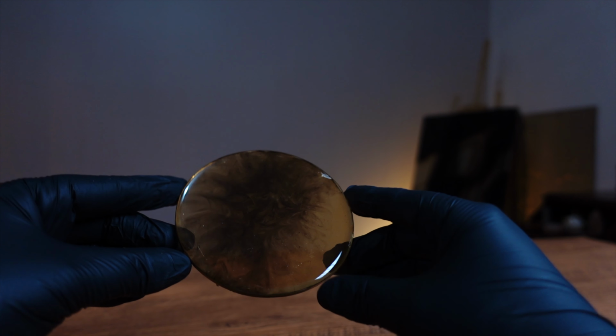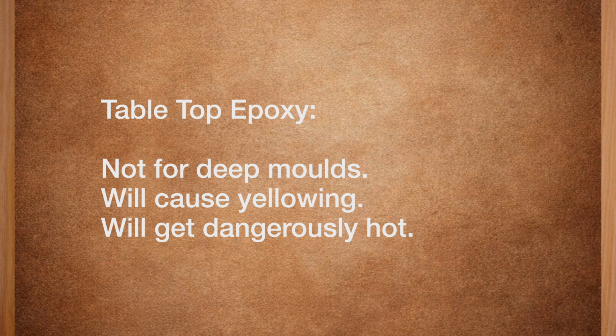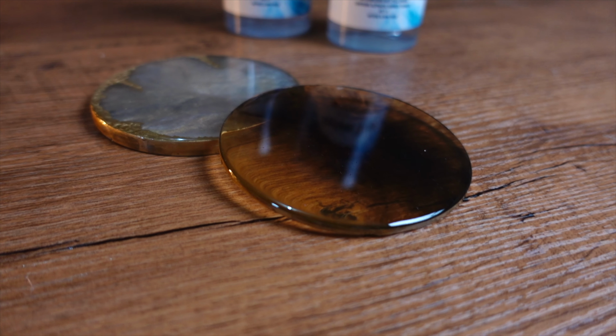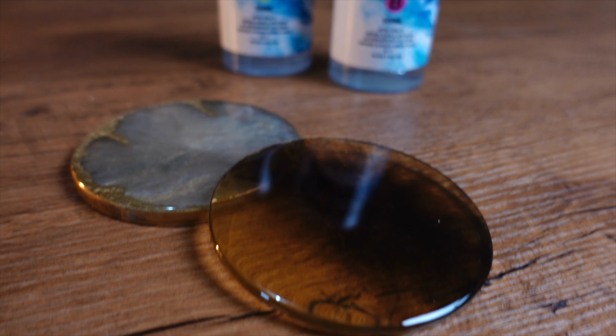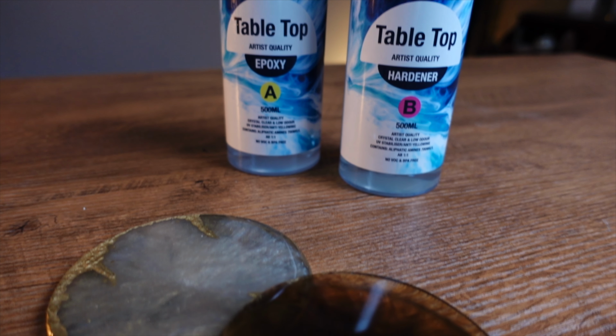It's important to remember this. Do not pour coating resin into a deep mold. Coating resin generates heat as it cures. And if you pour it in a deep mold, that heat has nowhere to go. It can cause the resin to crack, yellow, or get dangerously hot. Coating resin is made for flat surfaces. Use it that way and you will never have this problem.